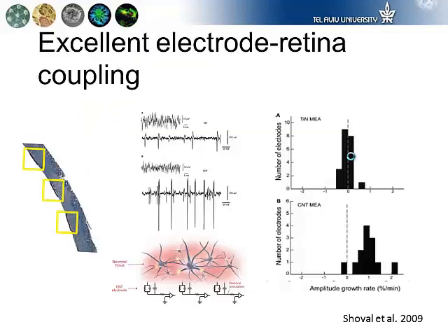So these are the important features. When it comes to electrical recording, as I said, you can get very high signal-to-noise ratios, just because, it's not something magical about the carbon nanotubes, it's just because it allows this very nice binding between the tissue and the electrodes. This is something you can see here. This is a cross-section of a retina that was cultured on carbon nanotubes for 48 hours, and you can see how nicely the tissue integrates into the carbon nanotube. So the two things become very intimately connected.